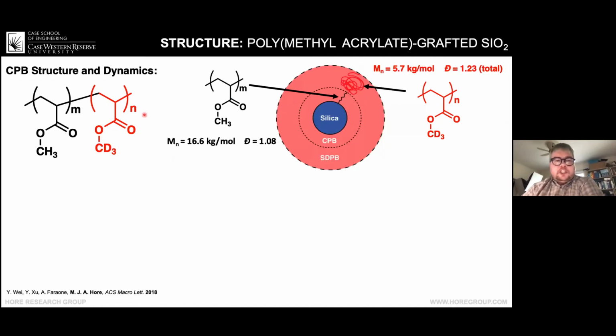To measure the structure of the concentrated polymer brush region, we had a hydrogenated block that was close to the nanoparticle surface. It was followed with a deuterated block farther away. So the molecular weight of the inner region was about 17 kilograms per mole with a low dispersity. And then farther out, we had a smaller molecular weight. We had 6 kilograms per mole. The dispersity of the entire polymer was relatively high, but it's okay. It's within the range that's acceptable for neutron scattering measurements.